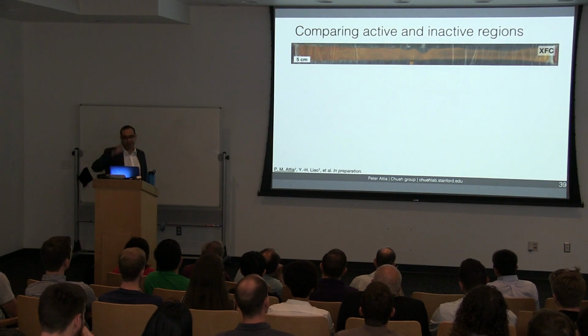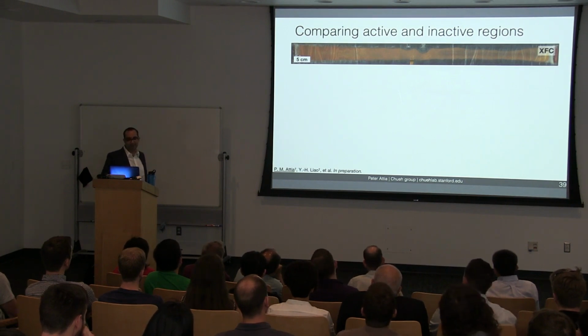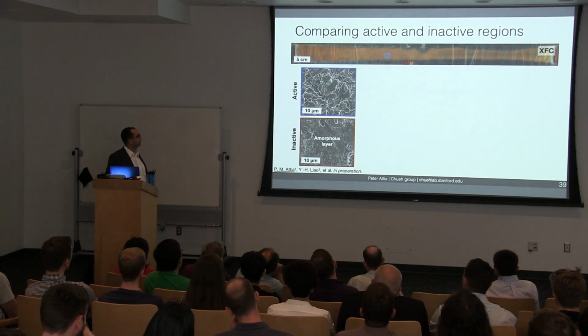So let's take a look at the cell that experienced extreme fast charging. If we perform top-down SEM of the active and inactive regions, we see that the active region basically looks like pristine graphite. But the inactive region has this amorphous goop all over the surface.